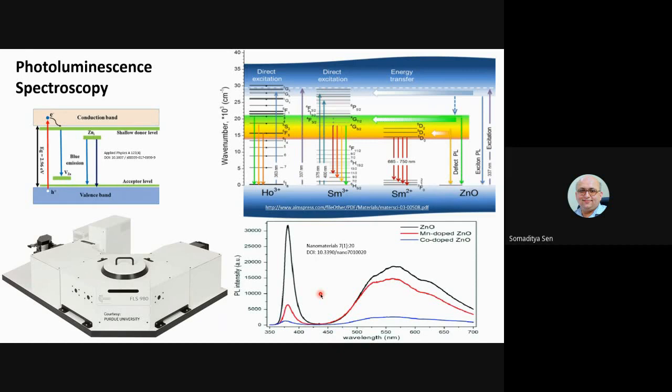So associated with the oxygen defect will be a zinc defect, or it can be a zinc in an oxygen place or oxygen in a zinc place. These are the latent defects of a zinc oxide material. Okay, there are other ones also, like zinc interstitials or oxygen interstitials. I told you about zinc interstitial before. Oxygen interstitial is also possible if there is a mismatch or a difference in the lattice formation. Okay, suppose you make it a little less crystalline, you can definitely put in an oxygen interstitial. There can be other reasons for oxygen interstitials also.